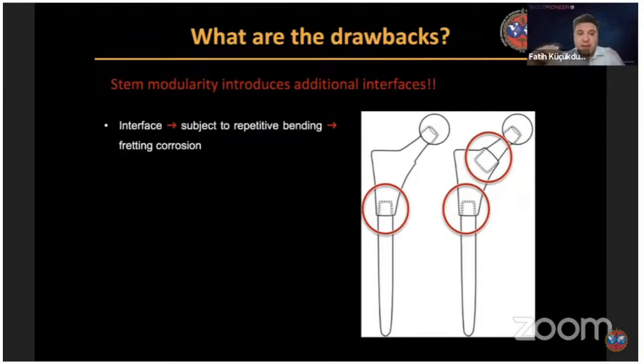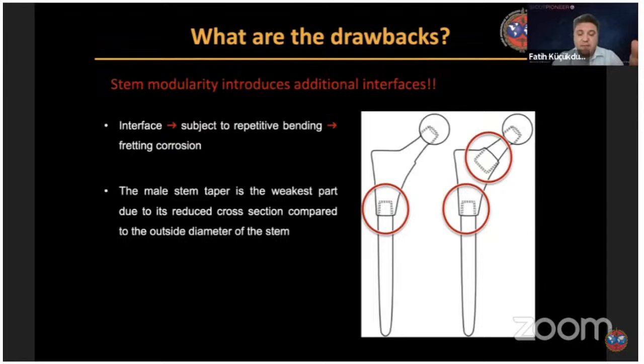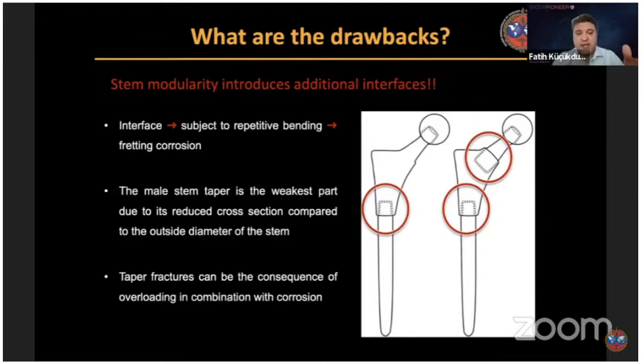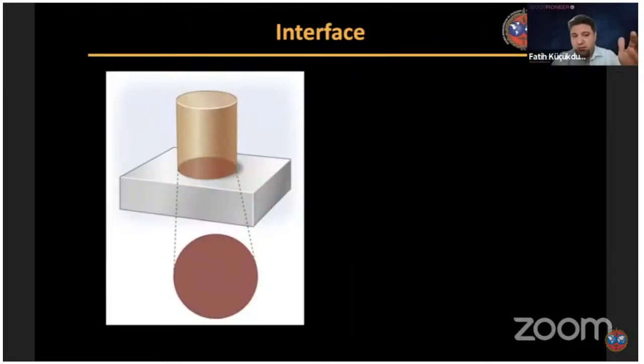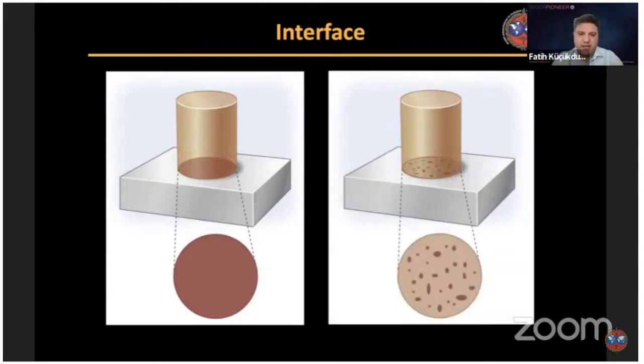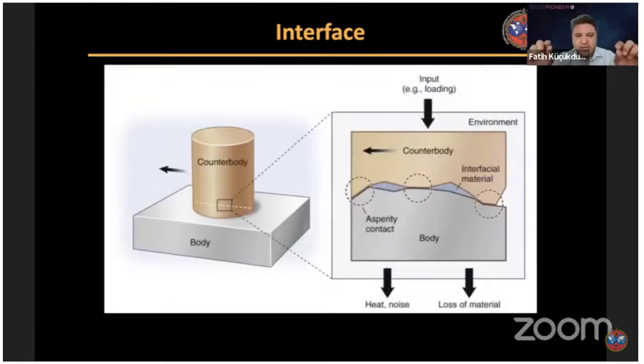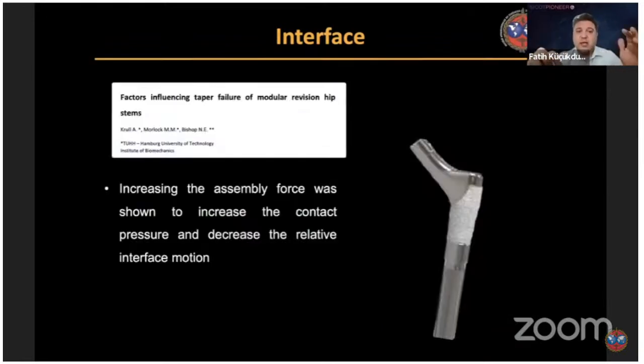So what are the main drawbacks? The stem modularity always introduces an additional interface, and this is the most important drawback, because every interface causes repetitive bending and corrosion in the end. And mainly the male stem taper side is the weakest part of these implants. It's always subject to overload and, in the end, implant failure, because when you look at the micro scale, the two sides of the interface do not touch perfectly, but it's more likely like the one on the right side, because on a micro scale there are always hills and valleys in the material. So when there is micro motion, it even causes some corrosion.